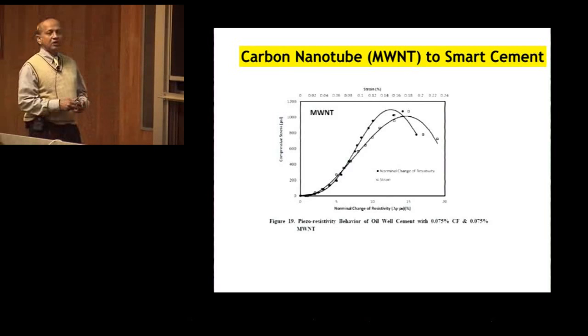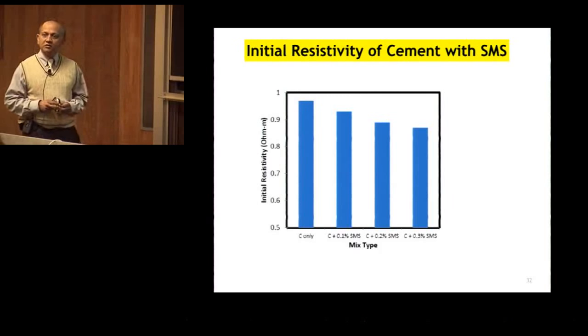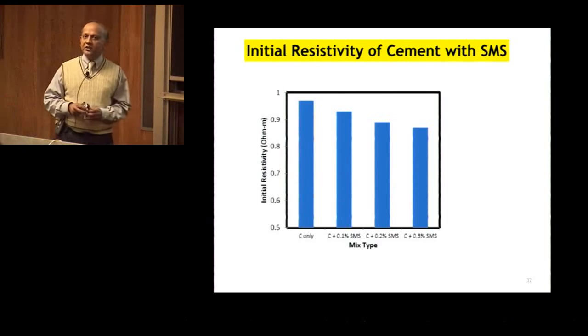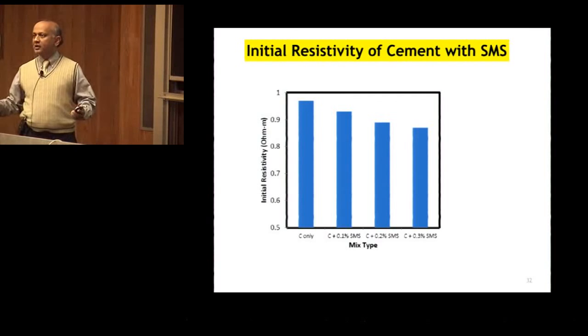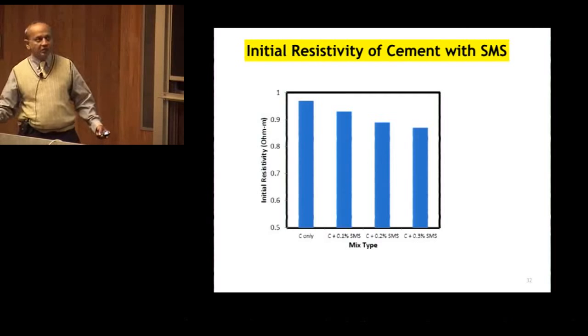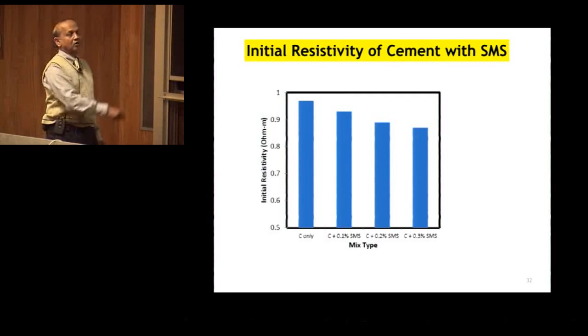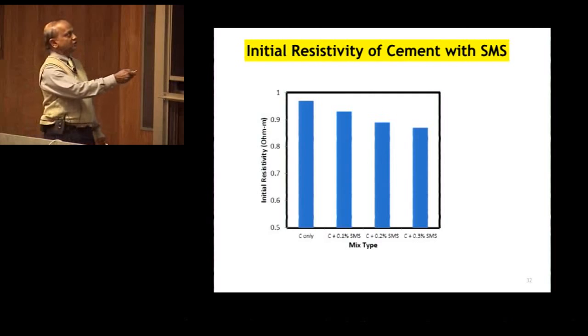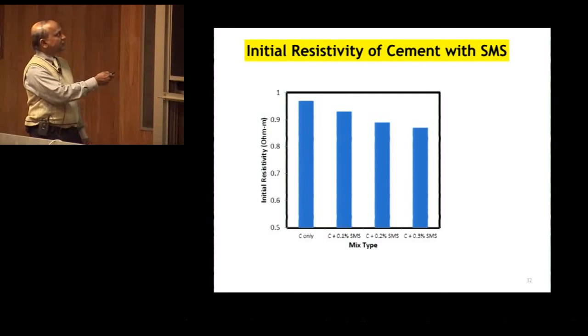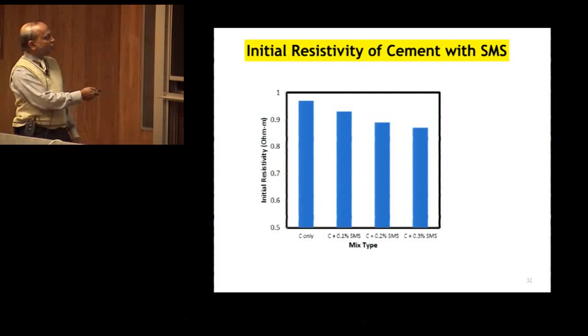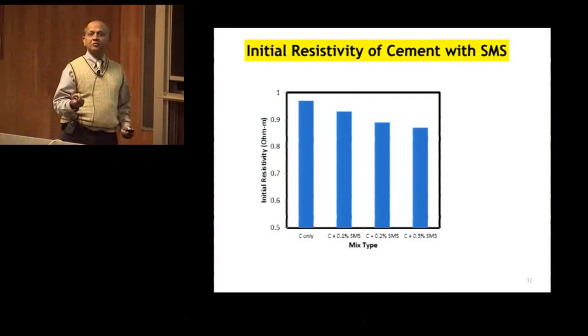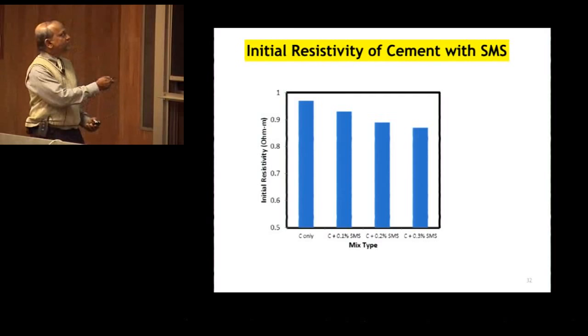Okay? Then we are also looking at the resistivity of cement, because cement in the field is not used alone. They put additives based on the environment. They have to put additives. They put a lot of sodium metasilicate. This is sodium metasilicate. And you can see, as soon as you put in the sodium metasilicate, resistivity drops. Even with very small additions, the resistivity drops. So from this, you can also control the quality of the mix, and also know that cement is being mixed with additives.